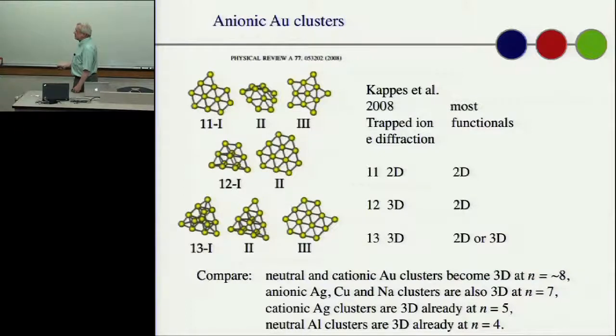Now for most clusters, you see here's aluminum. Of course, a 3-atom system would have to be planar. A 4-atom system could already be 3D. Neutral aluminum clusters are already 3D at 4. Silver clusters become 3D at 5. Here we see some clusters that become 3D at 7. Here we see some clusters that become 3D at 8.